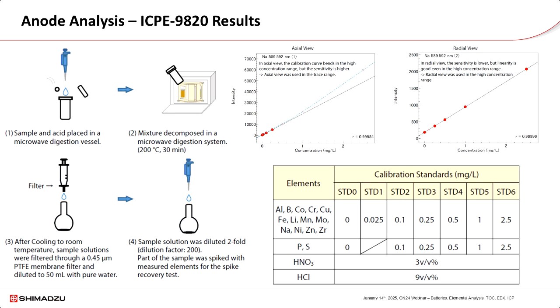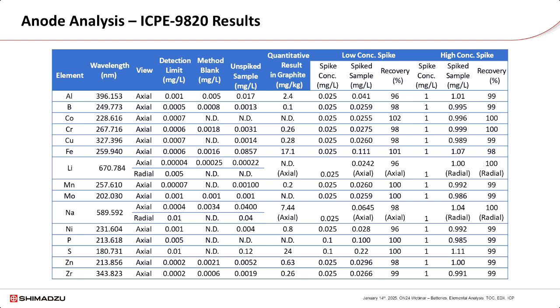Dual view and high salt tolerance of the instrument also allow for a wide dynamic range by selecting radial and axial for different elements, which is also possible to change and reprocess post-run. In this study, because we analyzed elemental impurities, which are trace elements, axial view was used for most elements except lithium and sodium, which were measured with both radial and axial view.